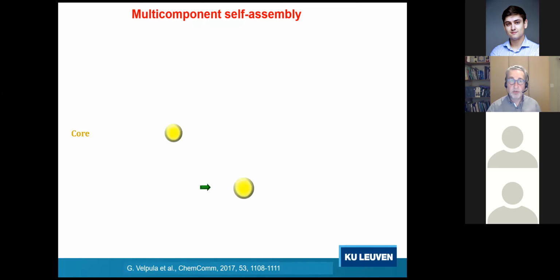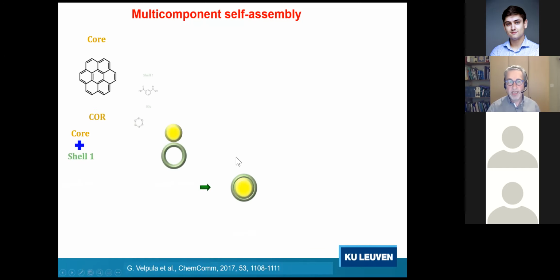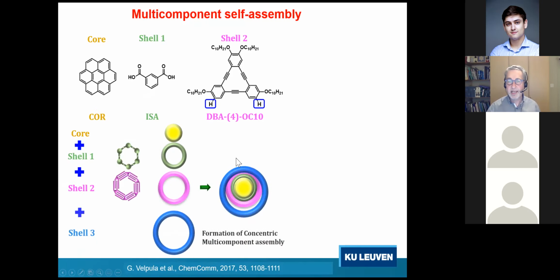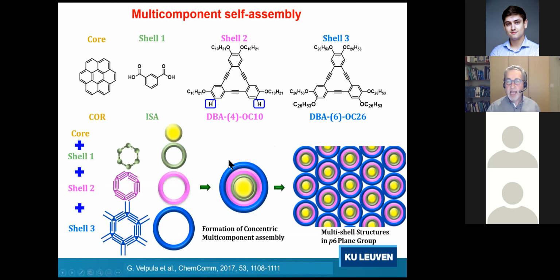So based upon a number of years of experience, we actually designed, and this is my group, but also the group of Professor Yoshito Tobe at Osaka University, we designed a system by selecting 4 molecules, the 4 molecules you see over here, and we selected them in a way that we predicted, or basically at first hoped for, that they would form the type of network that you see over here, where you have a coronene molecule, shown here with this yellow disk, that would be surrounded with 6 of what we call shell 1 molecules. The shell is shown over here, and by adding then the shell 2 and shell 3 molecules, we would continuously build larger shells around the initial structures to end up with this kind of morphology or architecture here at the right-hand side.